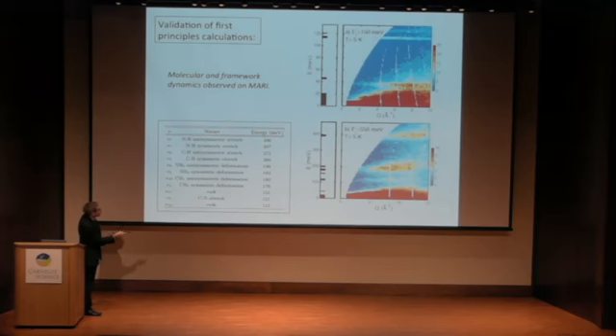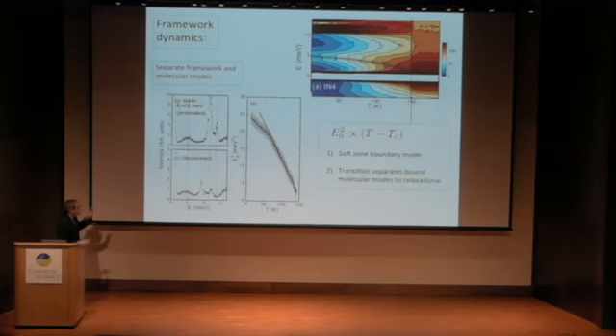You can see where you run into problems in these scans here. These are done on MARI, and what I'm trying to show you here is a comparison with calculations. The molecular and the framework dynamics strongly overlap at low energies. So the simplest way to separate the two is to deuterate the samples, to replace the hydrogen with deuterium. And that does 2 things. First of all, it reduces the cross-section, and also deuterium's heavier than hydrogen, so it changes the energy scale of the hydrogen-related modes.